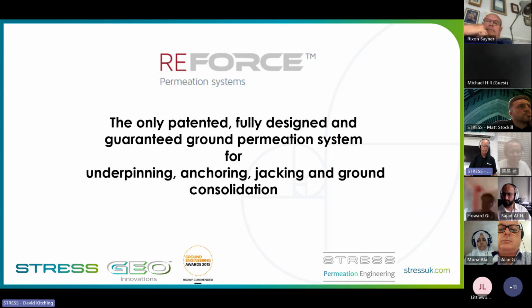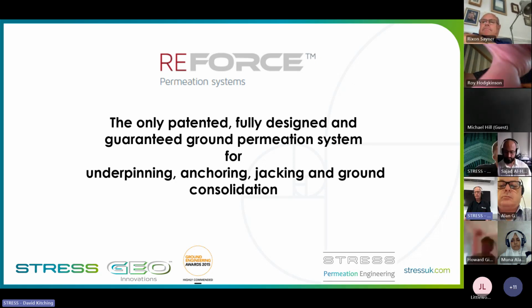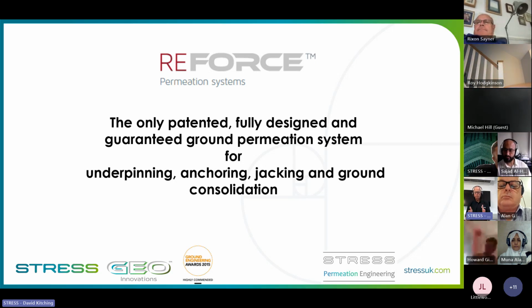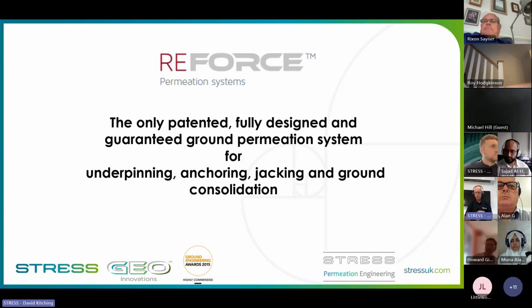No point in putting this expensive resin in the ground if we're not going to get any benefit out of it. So I asked him if he would do some strength tests, classic compression strength tests. So the good old 6-inch cube molds, steel cube molds, oiled up. We created the composite in there, let it cure, and then Simon had to take a sledgehammer to smash them apart, because this composite has bonded through the shuttering oil onto the steel, and we can't get it off. So we actually have to grind the surface clean. So there's a huge amount of adhesion.